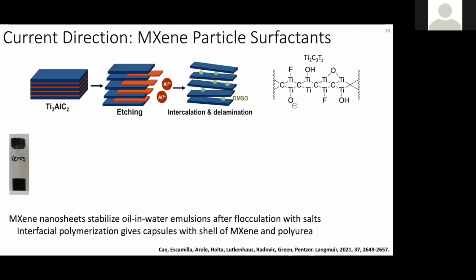Another current direction we're going is using non-graphene oxide based particle surfactants. So this is a collaboration with Professor Micah Green, with whom we have a joint student, Huishen, and MXenes are transition metal carbides or nitrides or carbonitrides. And so a representative chemical structure is shown on the top right. The big picture is you have this titanium carbide nanosheet, and it's decorated with different functional groups. So based on the synthetic method, these are normally fluorine, OH, and these bridged oxygen species.